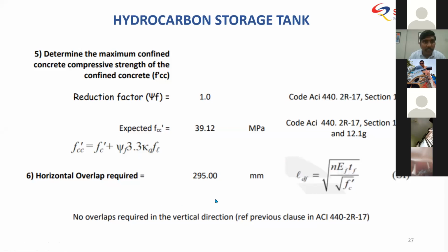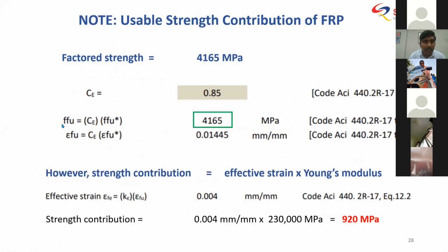The one thing that you need to understand is that the ultimate fiber strength of 4,165 MPa is what we get after application of this environmental factor. However, in actual practice, we are limiting the strain to 0.004. So if you multiply that with the Young's modulus of the fiber, strain epsilon into E, you will get the strength, right? So ultimately the strength that is provided by the FRP is only 920 MPa.